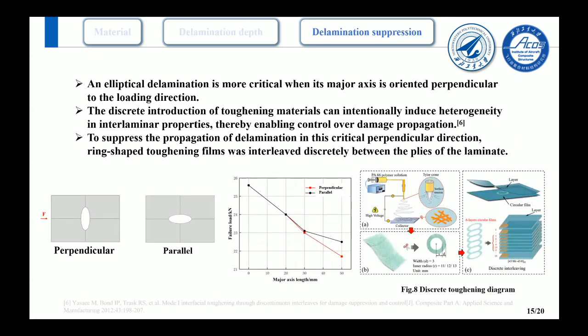Last but not least, we implemented a specific strategy to suppress delamination. Delamination damage incurred during actual manufacturing is not necessarily circular. Elliptical delamination is more prevalent. Our investigation revealed that an elliptical delamination is more critical when its major axis is oriented perpendicular to the loading direction.